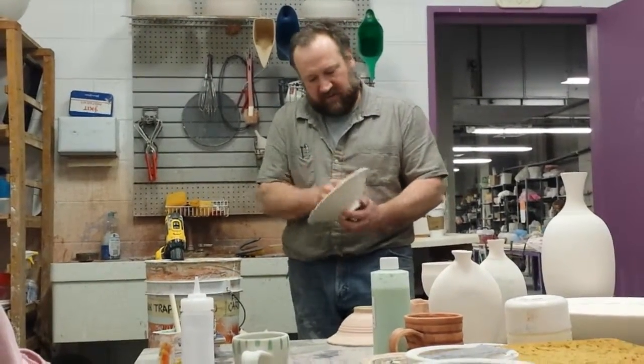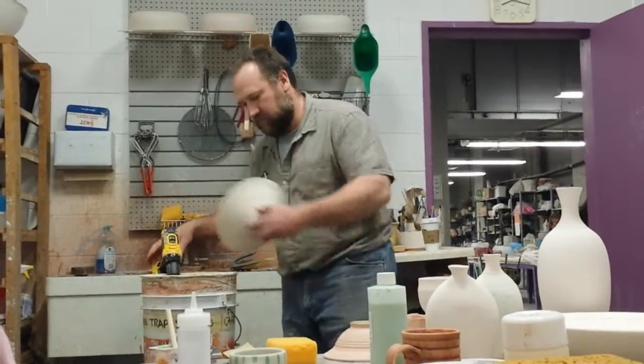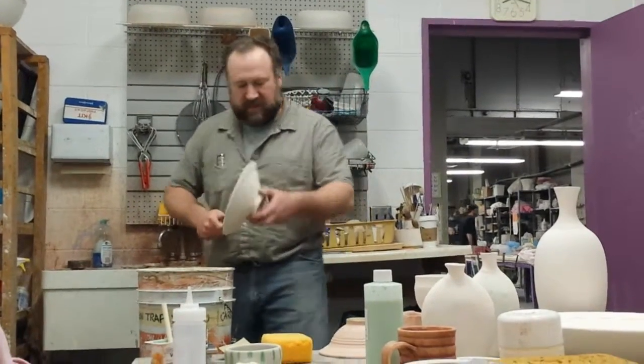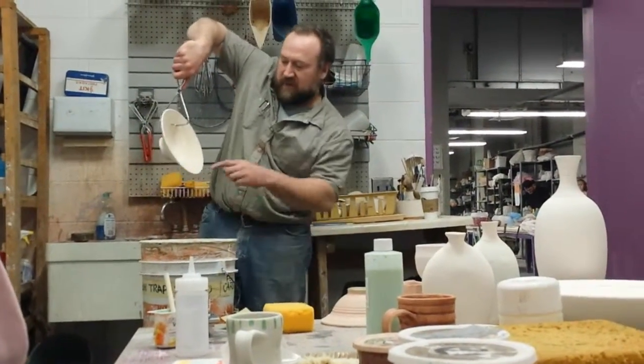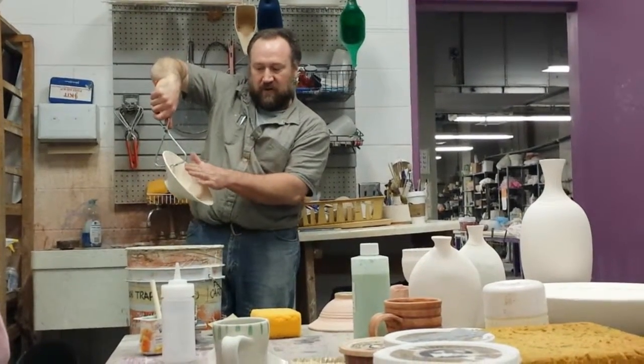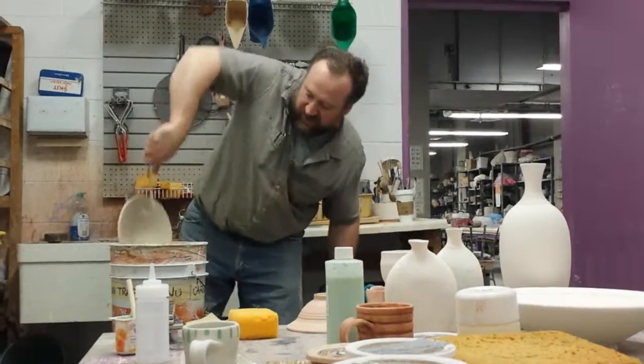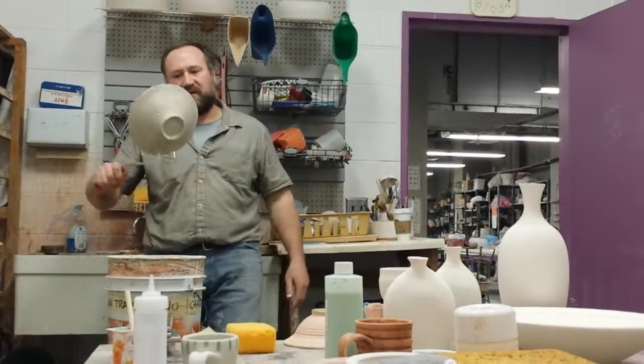Here I want the inside to be a little thinner and the outside to be a bit thicker, so I'm going to moisten the inside of the bowl first. Because this is so touchy with thickness, if I just dip it in and pull it straight out, the leading edge is going to be in the glaze much longer than the tail end of the bowl — so you'll get a whiter area fading into orange at the top, and little streaks of white coming off where the tongs are. You can battle that by immediately coming out and turning it the other direction.